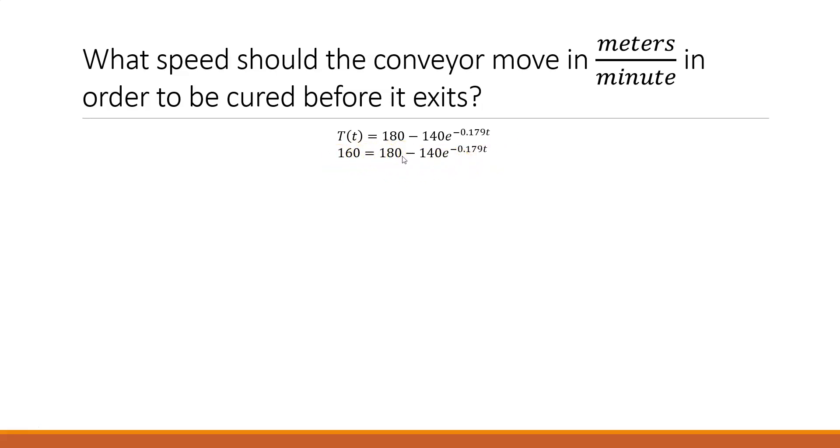So it's going to cure at 160 degrees. So now we just need to figure out what time that's going to take. And again, that's the benefit of the model. This is you starting into your first solution. So it's 160 degrees and we're solving for T. So we're subtracting 180 from both sides. And then we're dividing by negative 140. And then we have to take the natural log of both sides to get rid of that base E. And then we come in at 10.87 minutes. So that's how long it has to be in there. If it leaves before then, it's not fully cured. And if it leaves after then, it runs whatever risk it takes for being heated up too much. We want to get it out of there shortly after it hits 160 degrees.